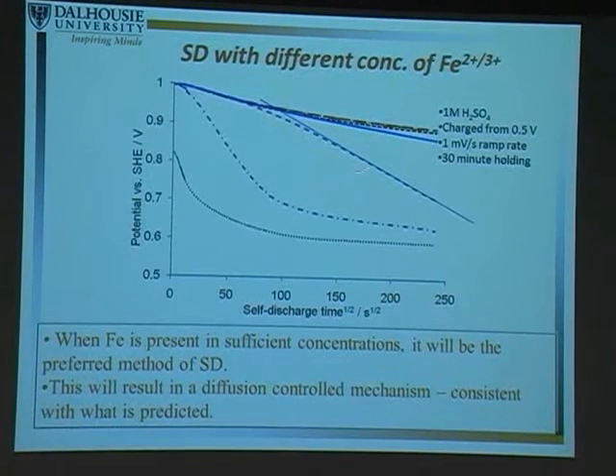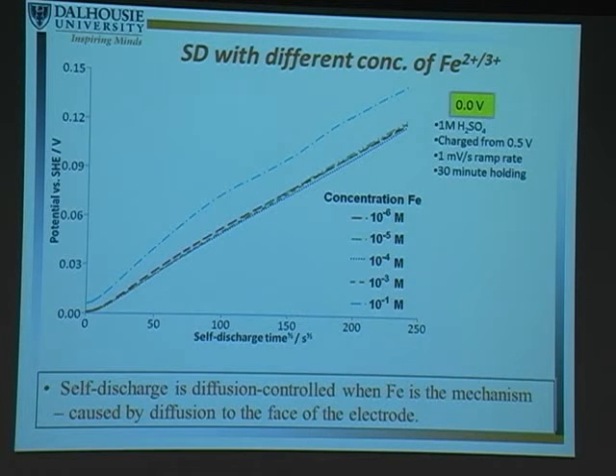And as we go to higher concentrations, we start to see a linear profile when we plot as a function of square root of time, indicating that it is a diffusion control process. And so, yes, iron diffusion here is going to be the cause of self-discharge. And anybody who's interested, we can talk about why this square root time profile, which is derived for planar electrodes, actually applies for porous electrodes. That was very interesting that we saw this as well. So that's with the positive electrode.